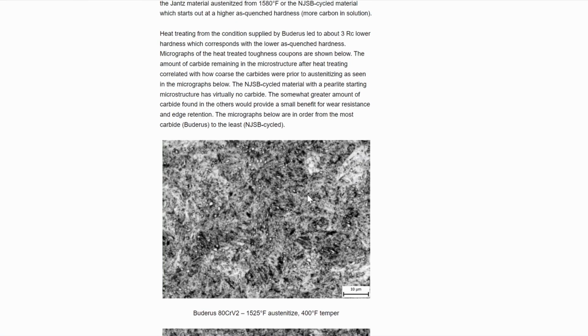So you might get a bit better edge retention, though your toughness hardness balance is a bit reduced, and you're going to have to heat treat the steel hotter to get similar hardness. So it definitely doesn't hurt to go through the type of cycling that I recommend in this article to get the fine spheroidized structure. You can get a little bit higher hardness toughness balance. But, you know, would our customer be able to tell the difference? That is always hard to say. You know, it's not like this Buderus material following a generic heat treatment is bad or terrible. But could it be optimized more? Probably.